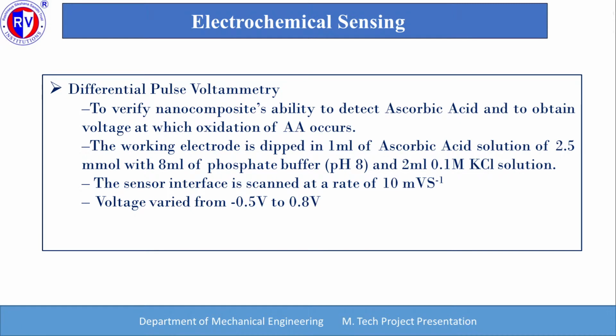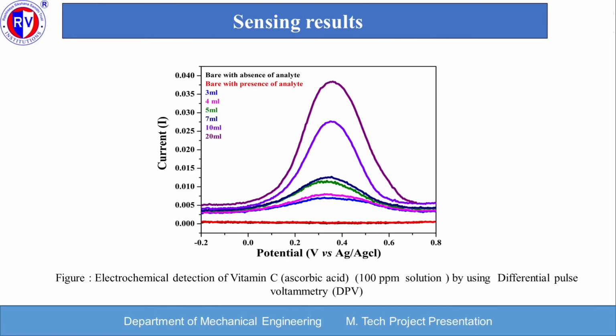The next step is to test our fiber in differential pulse voltammetry to verify the nanocomposite's ability to detect ascorbic acid and to obtain the voltage at which oxidation of AA occurs. The working electrode is dipped in 1 ml of ascorbic acid solution of 2.5 mM with 8 ml of phosphate buffer and 2 ml of 0.1 M KCl solution. The sensor interface is scanned at the rate of 10 mV per second. Voltage varied from minus 0.5 volt to 0.8 volt.